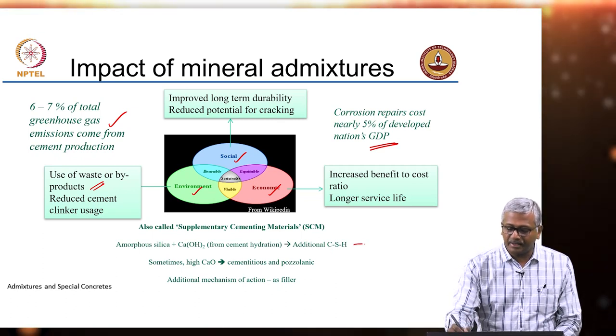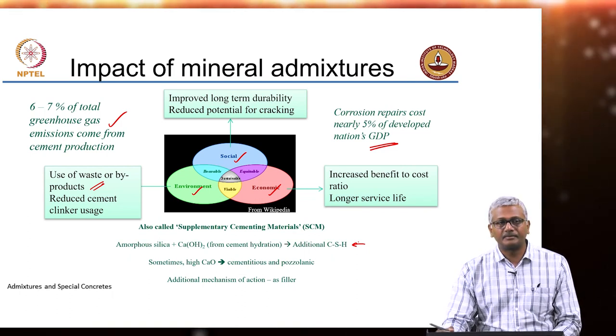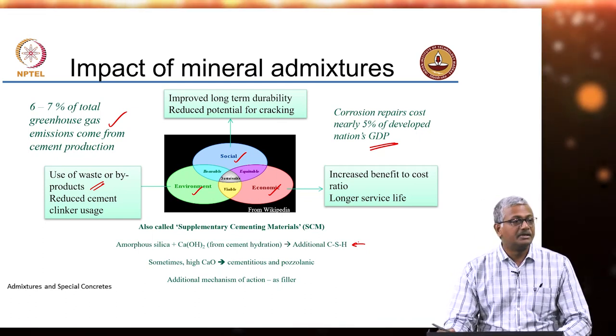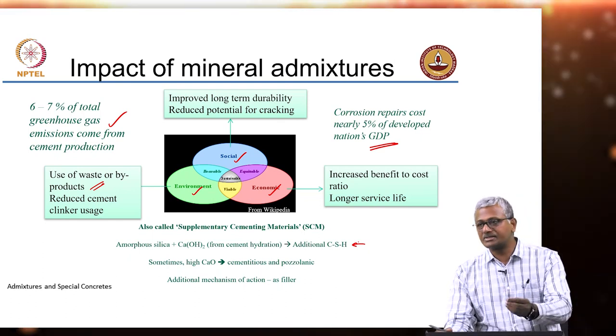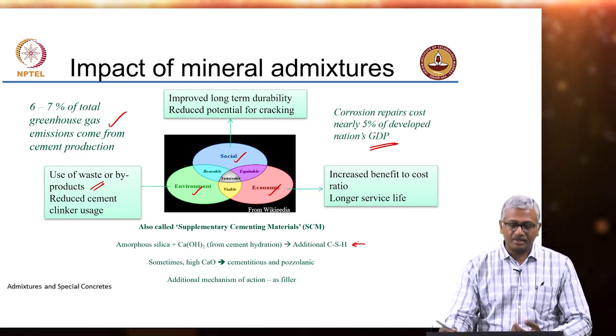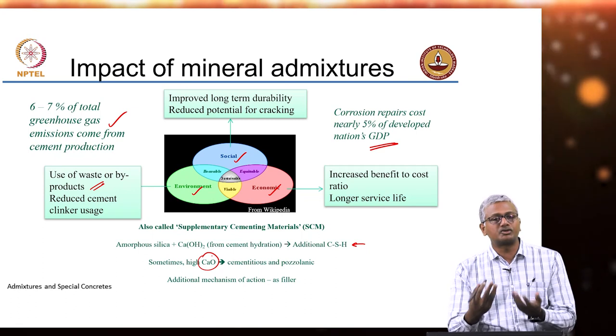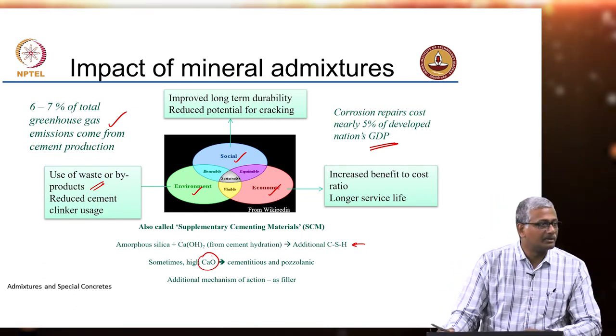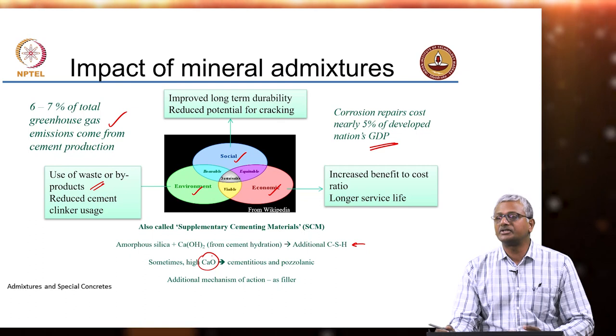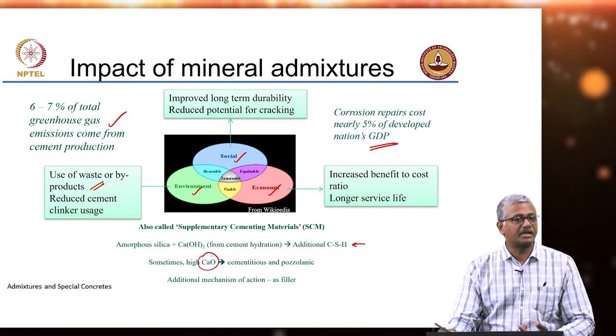The primary reaction is that amorphous silica from the mineral additive combines with calcium hydroxide from cement hydration to form additional CSH, which is better for blocking porosity. Sometimes the mineral additive may also contain calcium oxide and have a cementitious effect itself. For instance, slag can produce CSH without needing to combine with calcium hydroxide because sufficient calcium is provided by the slag itself. Additionally, mineral additives can act as fillers, producing concrete that is more dense and compact.